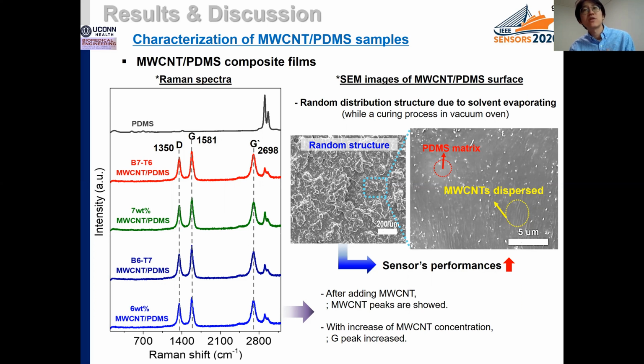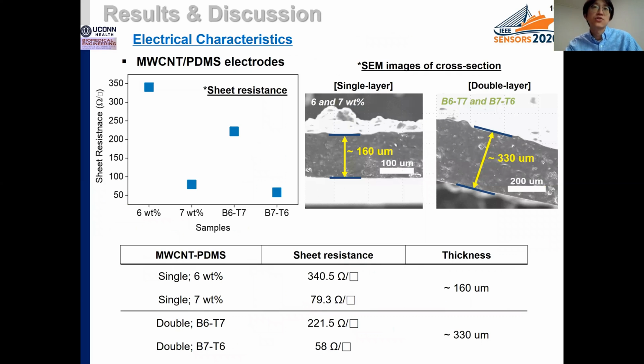So it's supposed that a random distribution surface would improve the sensor performance more than a smooth surface due to the increase of effective contact areas. This slide shows sheet resistance and thickness of composite films with different MWCNT concentrations. From the data, we found that the sheet resistance decreased with the increase of MWCNT concentrations.